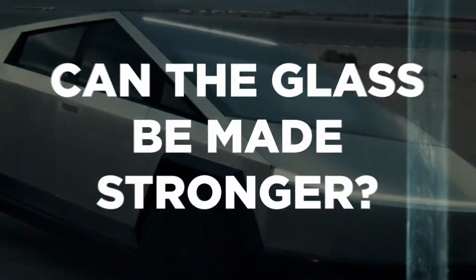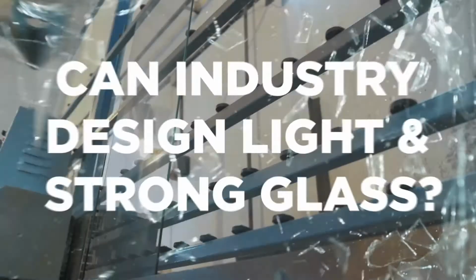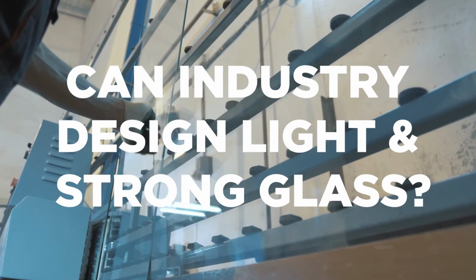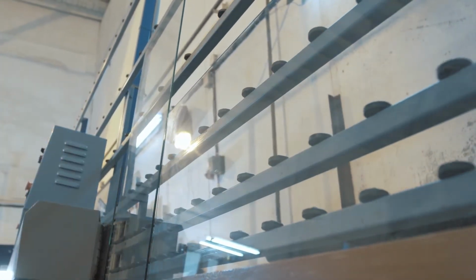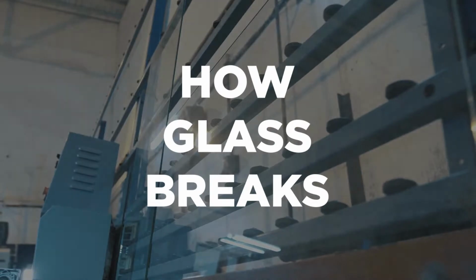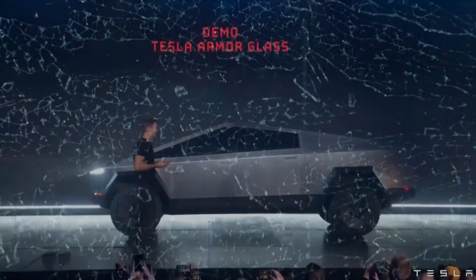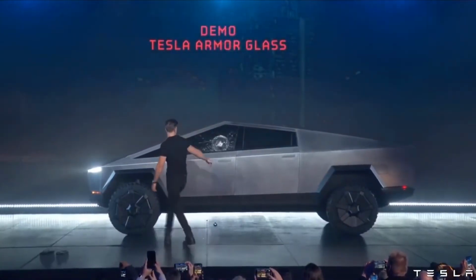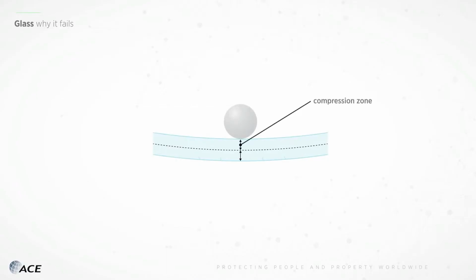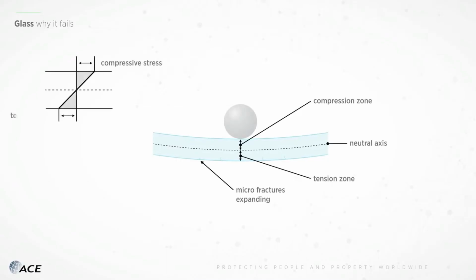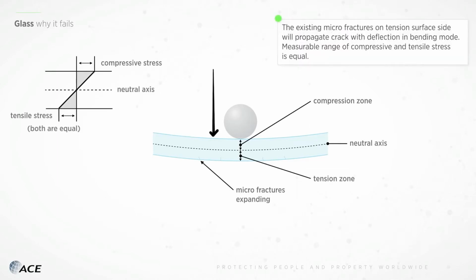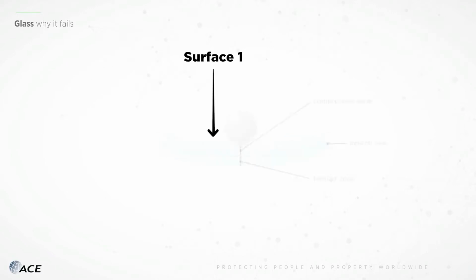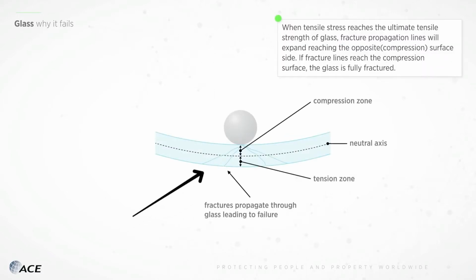So, can the glass be made stronger? And can industry design glass not to break while still not increasing weight loading? To accommodate this, we must consider how glass breaks. With the Tesla Cybertruck demonstration, the window broke when struck by a steel ball. Here's an important factor to understand. The breakage occurs not as a result of the steel ball hitting the exterior surface, or what is termed in the industry surface 1, but as a result of the tensile strength of the interior side, or surface 2, the side furthest from the steel ball, being exceeded.